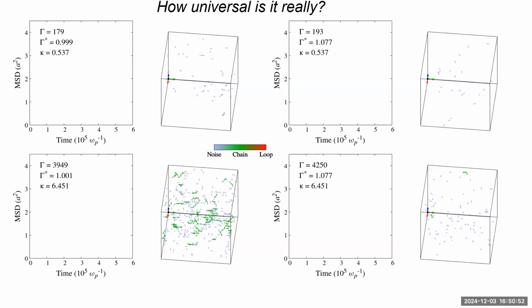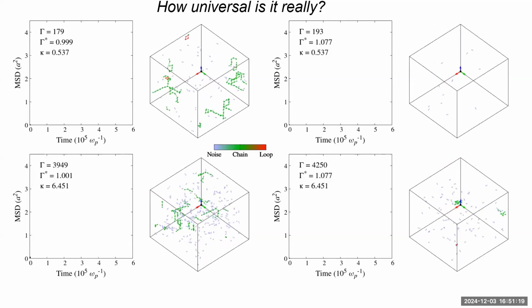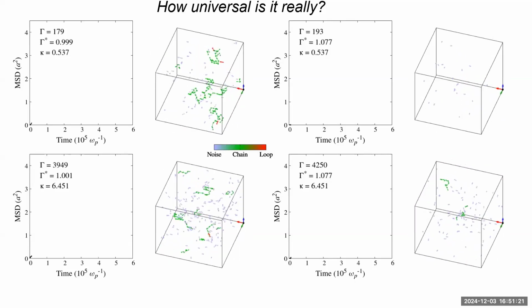So I'm showing you a grid of 4 simulations. 2 of them are very near the melting temperature, and 2 of them are a little bit colder than the melting temperature. 2 of them are at low screening, and then 2 of them are at high screening. So these 2 should have basically the same diffusion coefficient, while the 2 on the right should have a different diffusion coefficient. And while I run this, I want you to notice just how different the dynamics are.